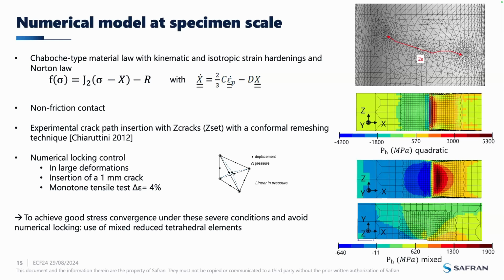So here you have a finite element model with a 1 millimeter crack insertion, which is subjected to monotonic tensile test with an amplitude of 4%. And as you can see, with a quadratic element, the hydrostatic pressure has convergence issues. So that's why I use mixed reduced tetrahedral elements to achieve good stress convergence under this condition and avoid any numerical locking. These are elements with one extra pressure degree of freedom at nodes.